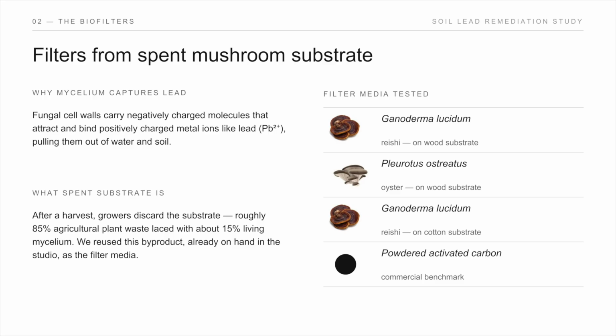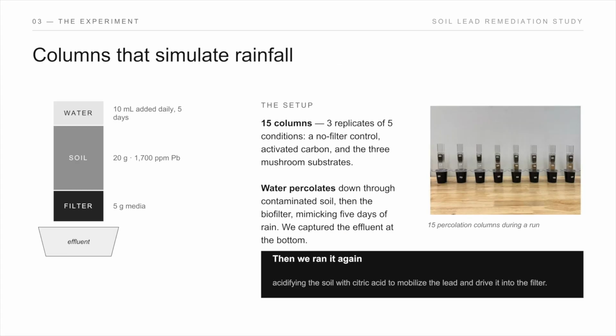And the key takeaways that we found. Well, let me describe exactly how we tested that. So we basically mimicked hydrology. We had water filtered through the soil, then it went through a biofilter, and then we captured the water and we tested all three. So, how much lead was still left in the soil, starting from that 1,700 parts per million, how much got into the biofilters, and how much got into the water. The first experiment showed that there was very little mobility. It's hard to get the lead out of the soil using normal hydrology.